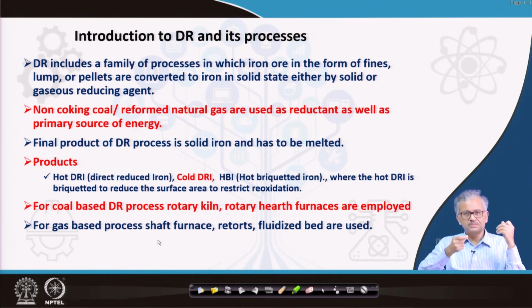If you have reductant inside, it will automatically get reduced. So there is no gas flow, basically retort. So it is externally heated from the side, and heat penetrates in the radial direction from the surface towards the center, and then the material gets reduced. So the tunnel kiln is a kind of retort, and there is the fluidized bed reactor, and the shaft furnace.